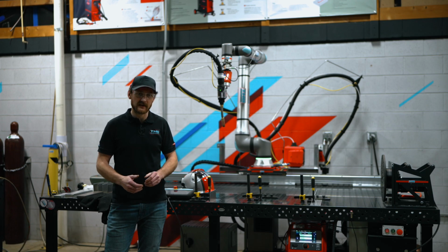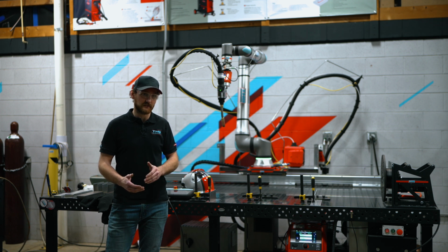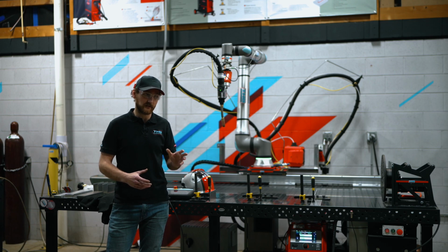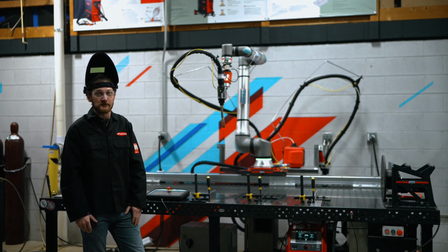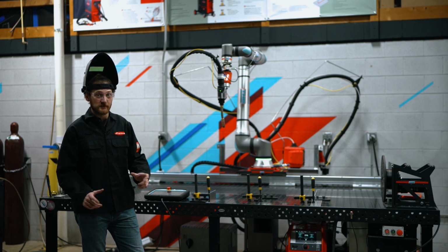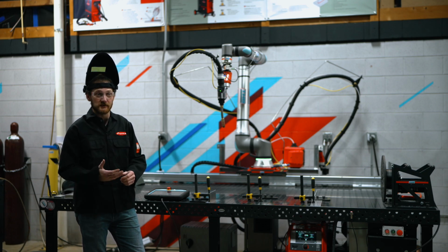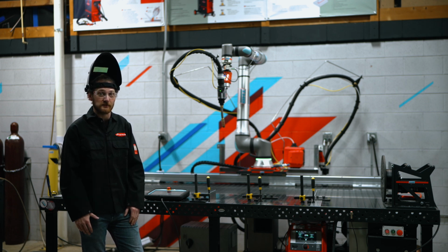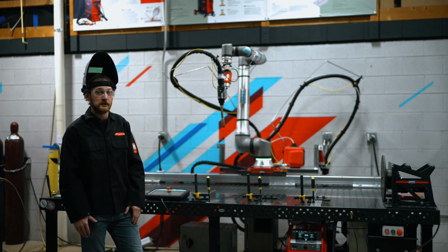And then you have, say, the mix processes that will actually have, say on CMT mix would be a PMC hot side, CMT cold side. So you can get kind of the heat punch to get it to wet out, and then kind of the cold side to bridge gaps. And kind of in tandem with that, you can get more of the stack of dimes TIG appearance if you're looking at aesthetics. So in this example, we're going to be using CMT mix, which is mixing PMC with CMT to either give you the stacked dimes appearance or to help with gap bridging and further reduce heat input into the base material while still allowing the weld to wet out and get penetration.